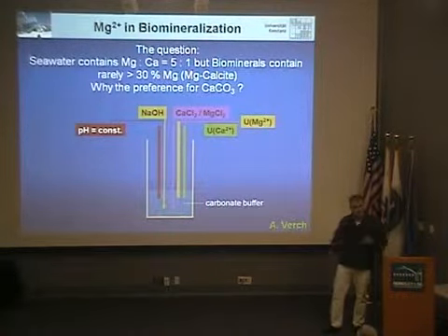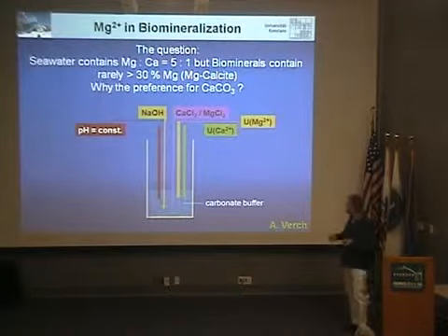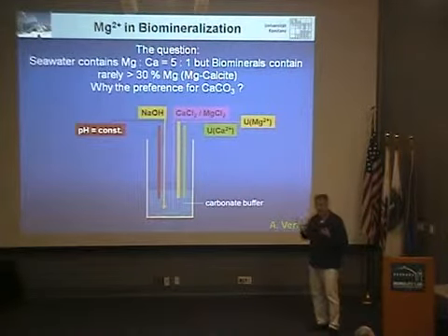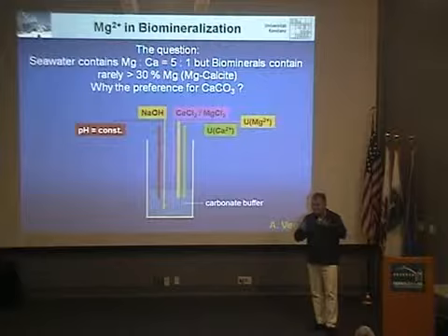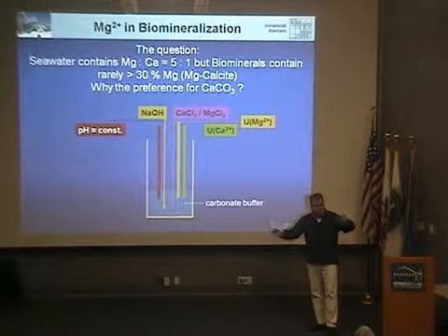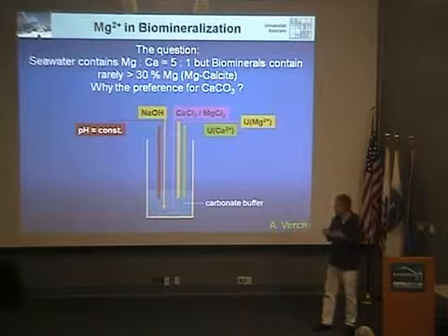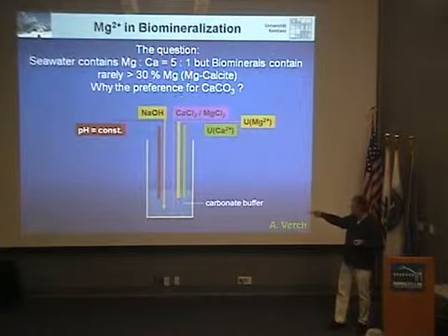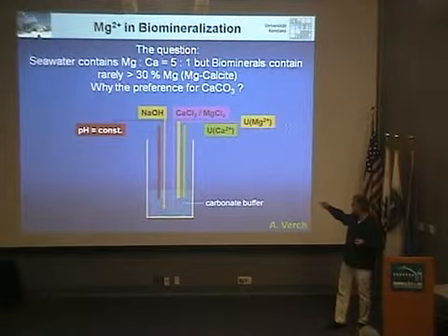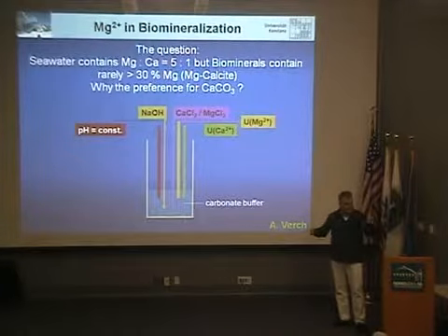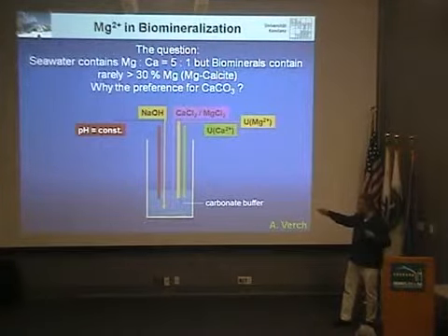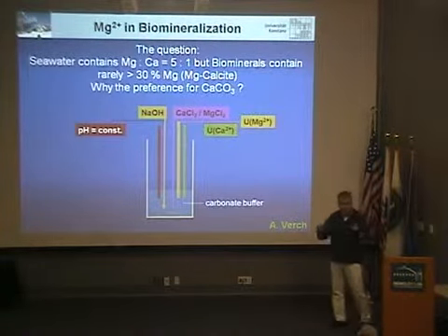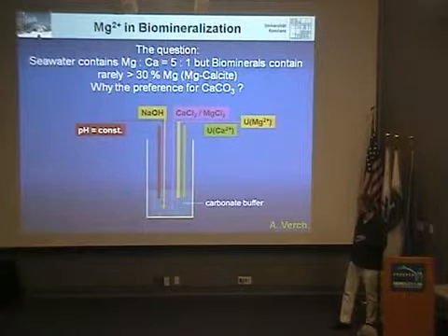So what happens upon formation of these calcium carbonate deposits in biominerals in seawater? And where's the magnesium going? And one intriguing thought we had, if there's prenucleation clusters, may it be that the prenucleation clusters expel the magnesium and just like more calcium carbonate formation rather than magnesium carbonate? So we set up an extension of our titration experiment and added a second electrode, which is magnesium sensitive. So we are measuring magnesium ions in solution, calcium ions in solution. We added calcium chloride and magnesium chloride continuously, and we kept the pH constant. So it's the same experiment now, just extended for magnesium carbonate detection.